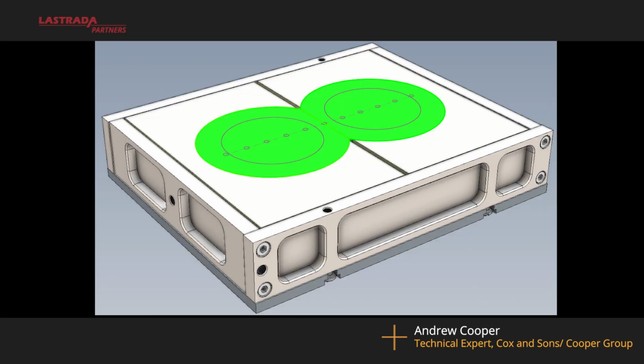Currently, the mean of the 5 central measurement locations is used in the AASHTO method. So if you look at the picture on the screen, you are taking the 5 central X's or crosses on those 2 pucks and looking at them and taking the mean of them for the AASHTO result. Those 2 pucks are pushed together along the line, which means that you have no aggregate interlock there. If the person doing the sawing is not a great saw, you have a void there as well, which material could flow into when you start to run the wheel backwards and forwards. It is really a very poor place to take the measurements.